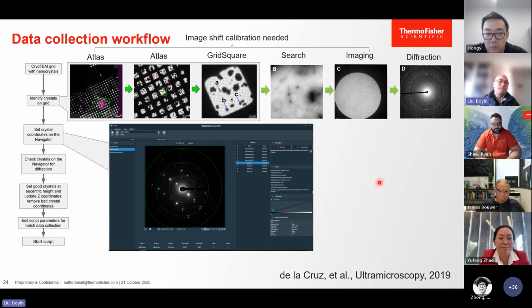So for data collection, this is the workflow. After you've got your cryo-TEM grid with nanocrystals, first you get an atlas, and then find a good grid square, and get the image of the grid square, and find the crystal you want to image. Then increase the magnification, and find exactly which part of the crystal you want to image. Then insert the 20 micron C2 and aim at the crystal and get a diffraction pattern. You really need to calibrate the image shift between all these magnifications so that you don't lose the crystal, and also minimize